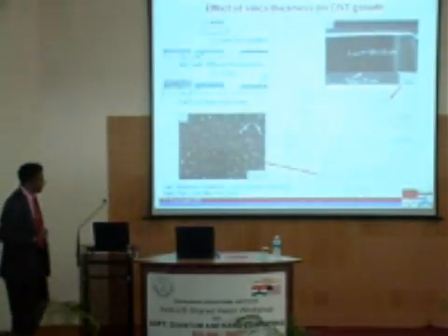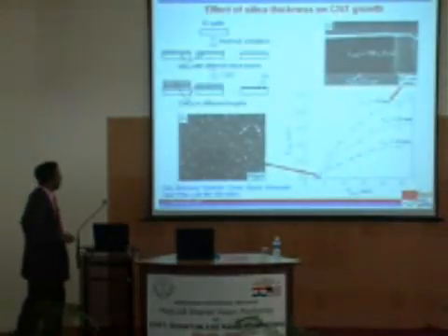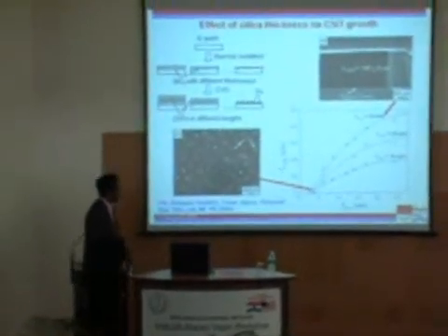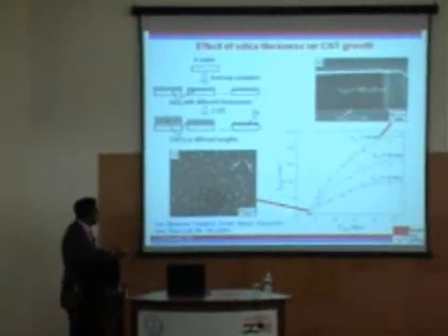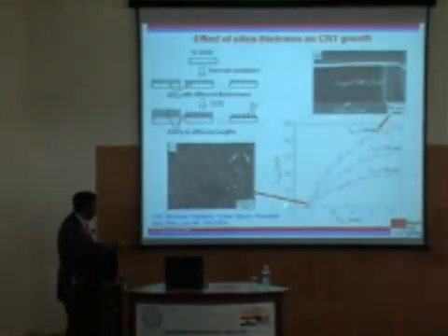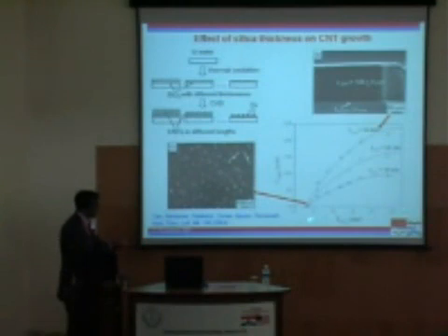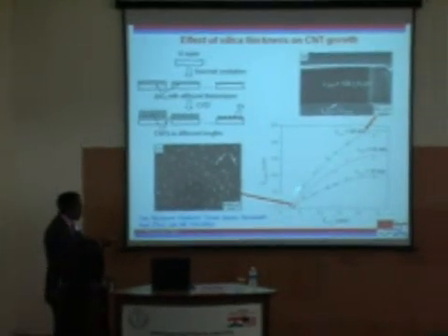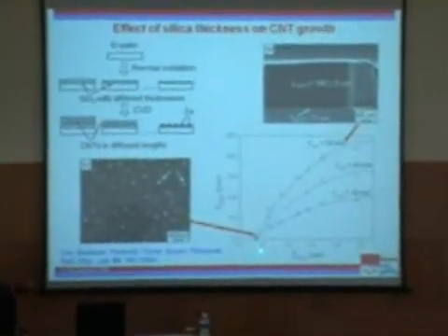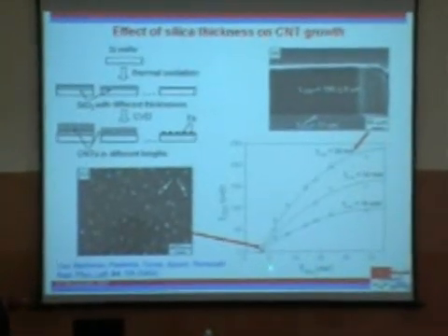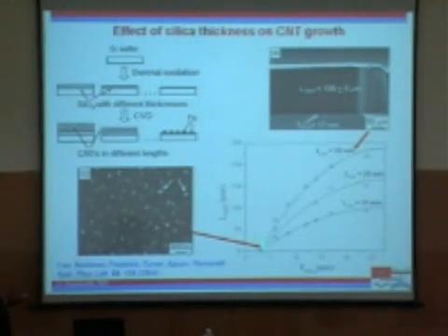Okay, there is another very interesting way in which you can control the lengths of carbon nanotubes, and that is very non-intuitive. I'm going to very briefly touch upon this. You can see that this is the length of the carbon nanotube, and this is the silica thickness. So the thickness of the silica under layer actually plays an important role. So below a critical thickness, you actually get no growth, which is not surprising because we do get selectivity, and that's what this shows.